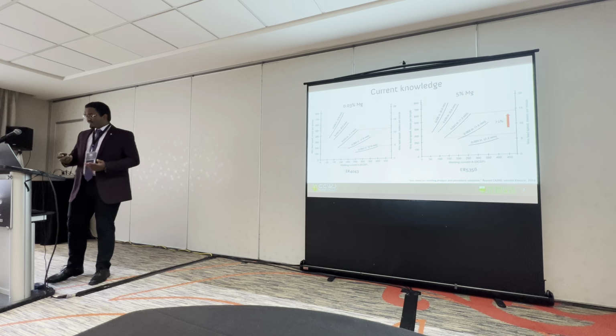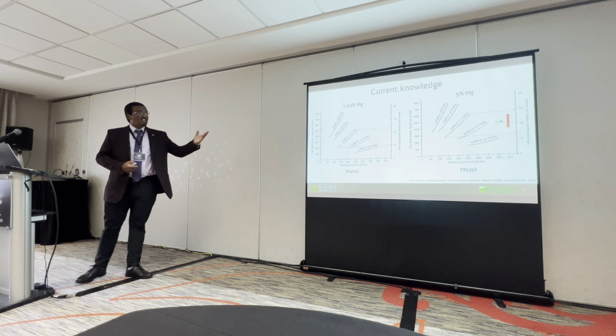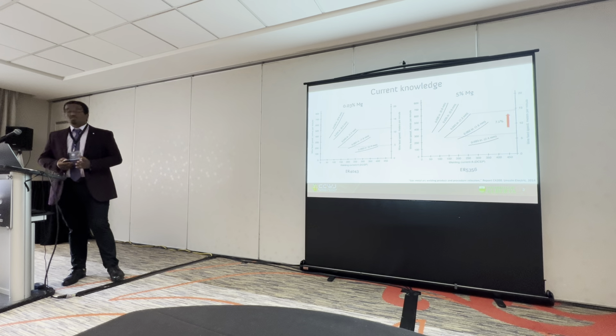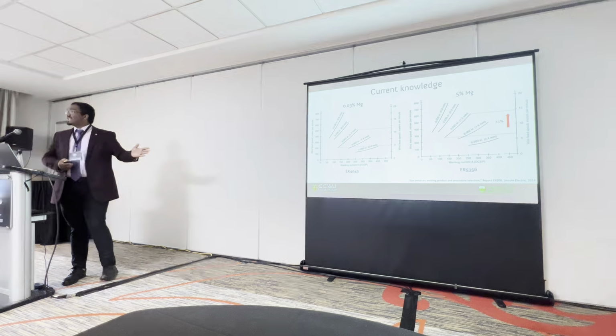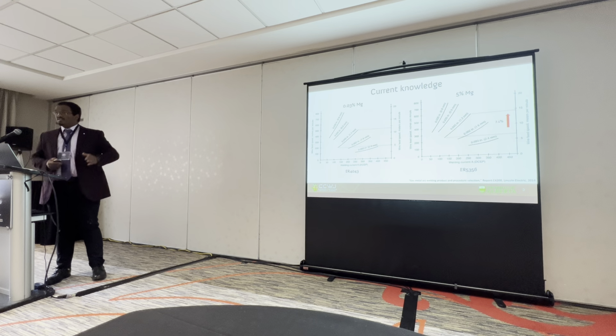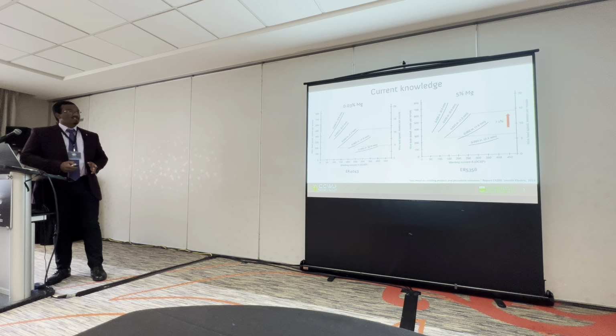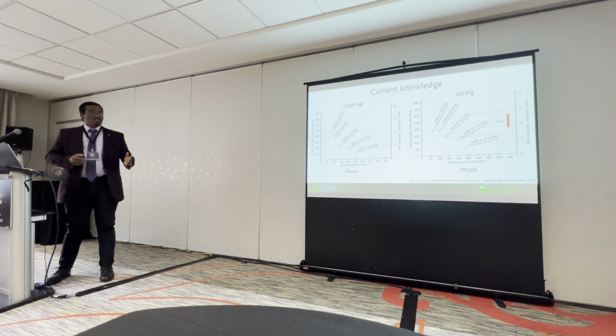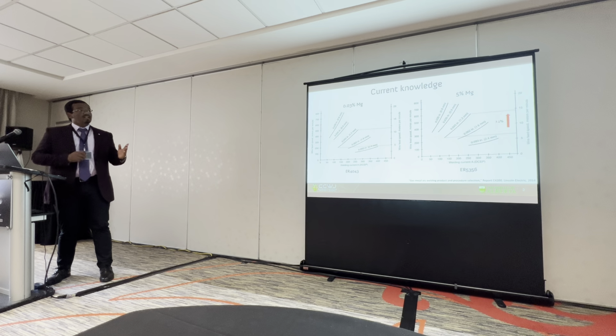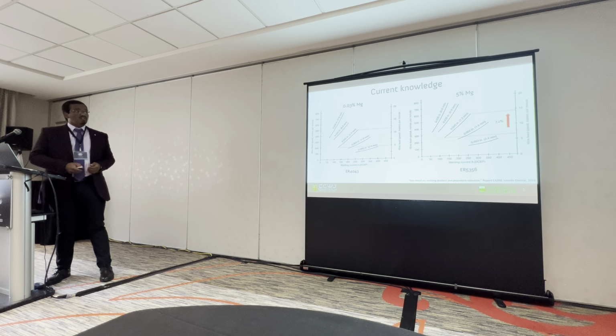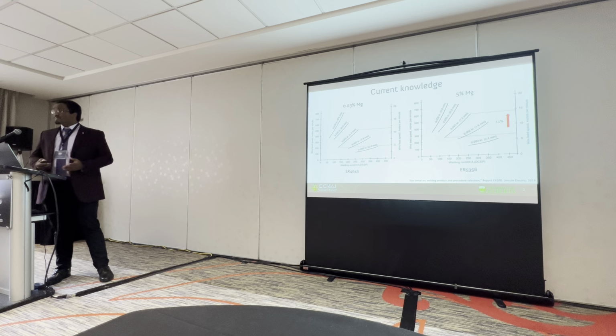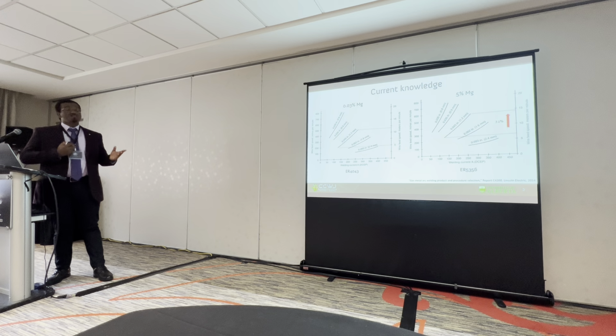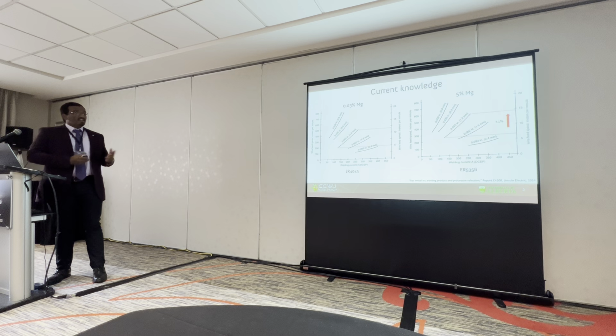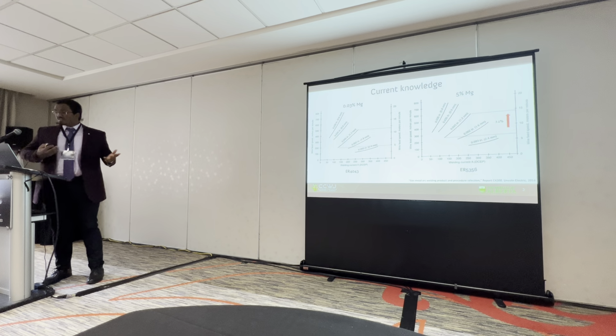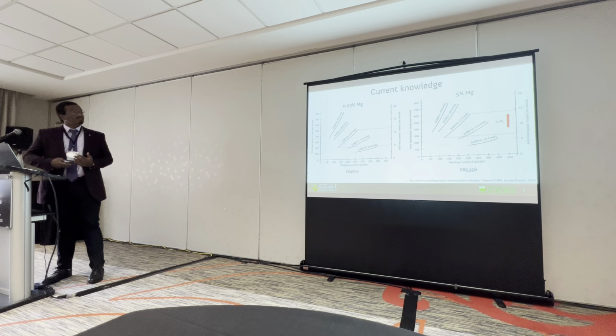So the current knowledge. I have two plots which show the wire feed speed versus welding current for 4043 and 5356. One has 0.03% magnesium and the other has 5% magnesium. These both are taken from the Gas Metal Arc Welding handbook of Lincoln Electric, and you can see there is an increase of around 7.1% in wire feed speed with an increase of 5% magnesium. This is already known, but I just wanted to show that it is already widely established.